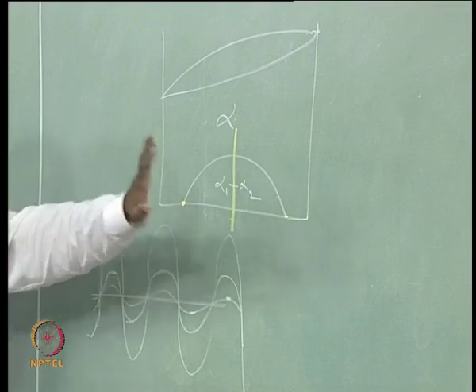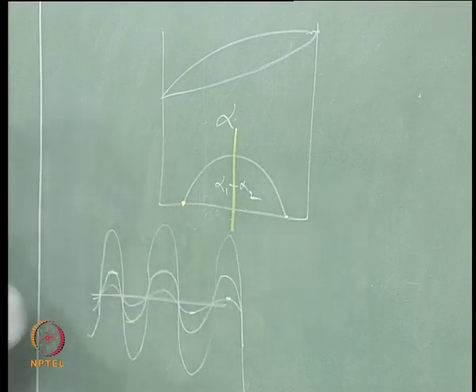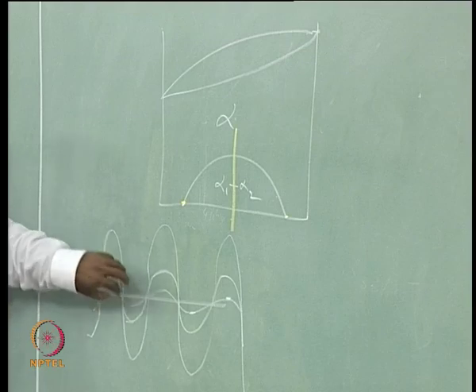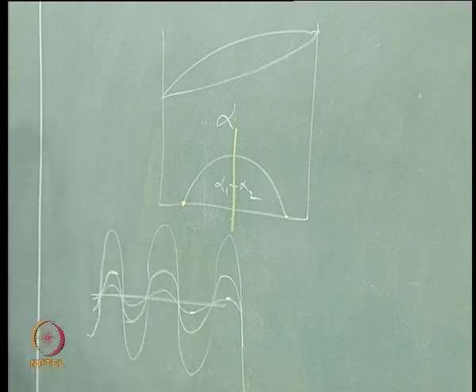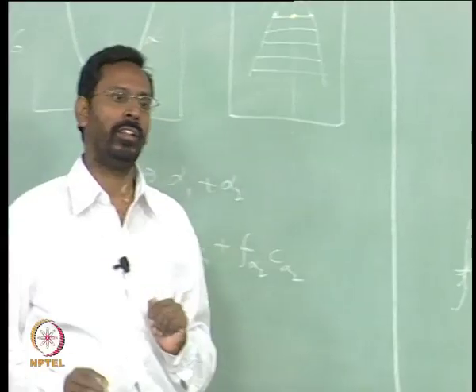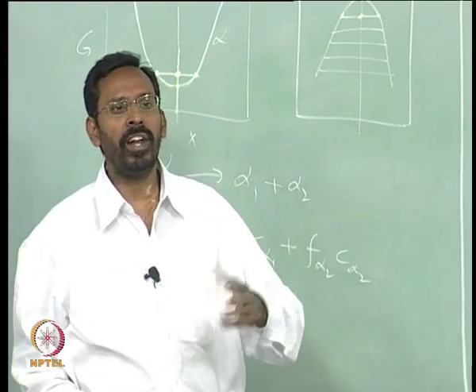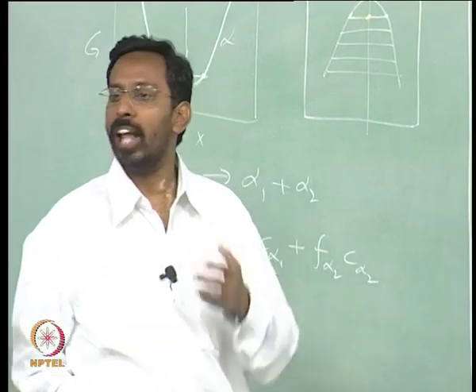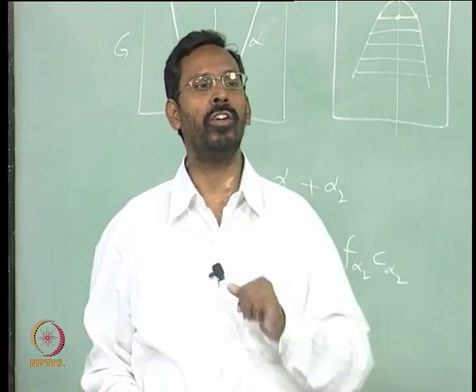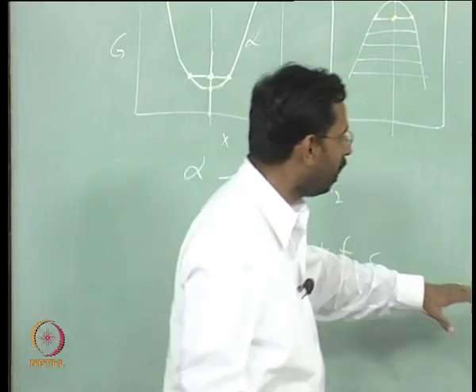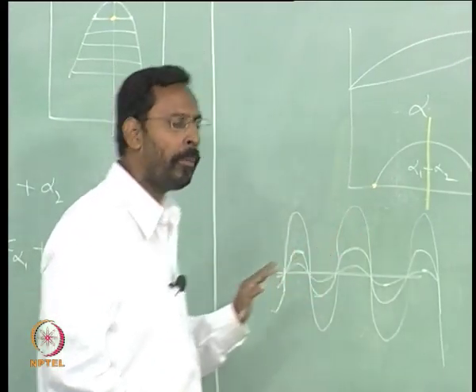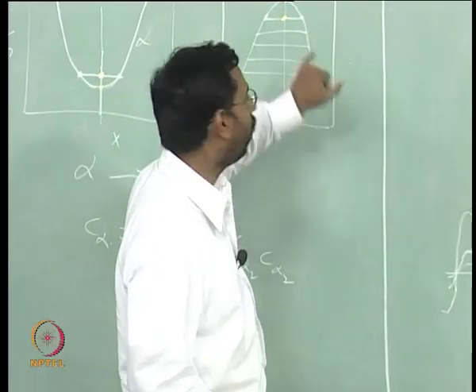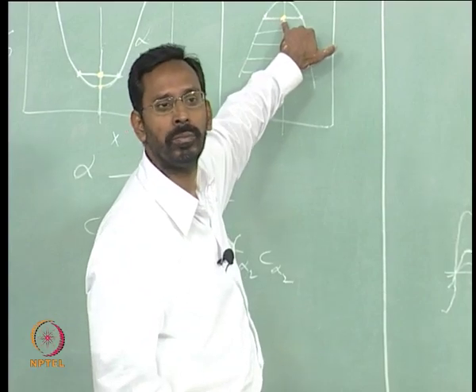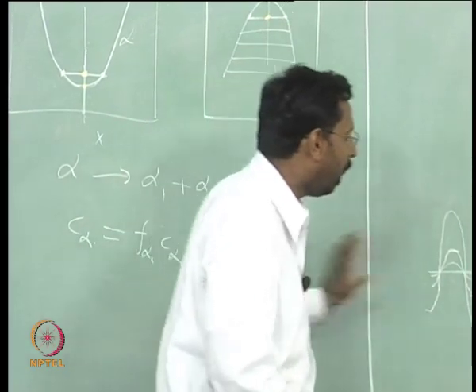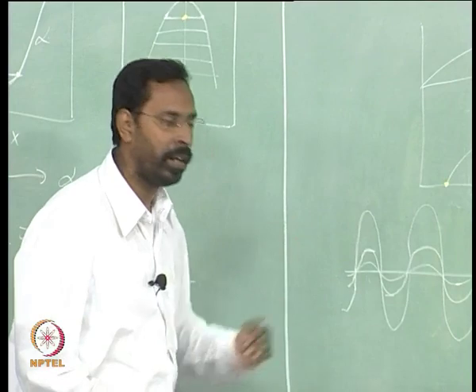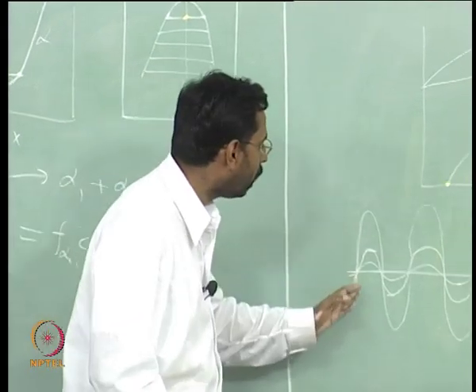Only when the whole growth has completed, you will see that this would be a different composition, this would be a different composition, and this happens homogeneously throughout the sample, whereas a precipitation does not happen homogeneously. It happens heterogeneously at some heterogeneous nucleating sites, whereas here this happens throughout. Why does it happen throughout? Because wherever it can happen, this is stable. So, you can see a homogeneous nucleation can happen in this kind of a situation, and that keeps on growing,